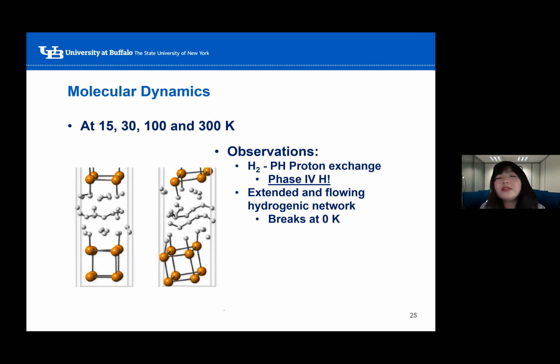To better understand the mobility of the molecular hydrogens, we carried out molecular dynamics simulations at finite temperatures, and we observed the proton exchange between the molecular hydrogens and the PH units, which resembles that of the phase 4 hydrogen. And at finite temperature, it can form a one-dimensional extended and flowing hydrogenic network, but this breaks at 0 Kelvin.